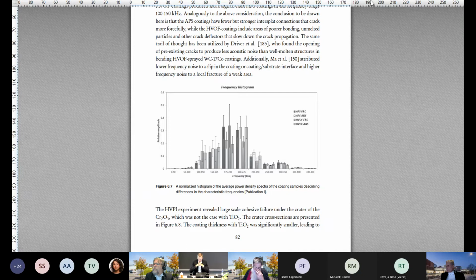I admit it was a bit of a question mark, to start, what will come out of it. But then I did see some trends, and so my hypothesis is that higher frequency of the crack means basically higher crack velocity, so a more severe crack, and lower frequencies could be micro cracking or crack deflecting a lot, and the higher would then be basically a major crack straight through.